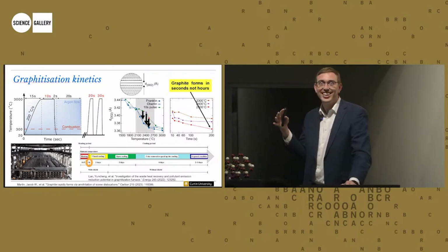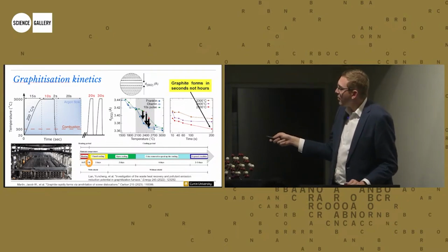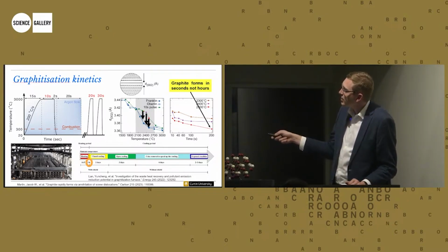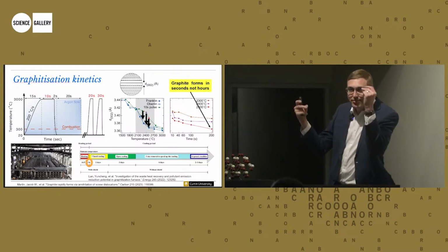It's fast. What had happened is everyone had assumed that this process was first order, and they'd measured the kinetics on this side, and they found enormous barriers. But it actually turns out to be a second order process, which means that it speeds up as you get towards the critical point, which means that once you pass the critical point, it happens like that.